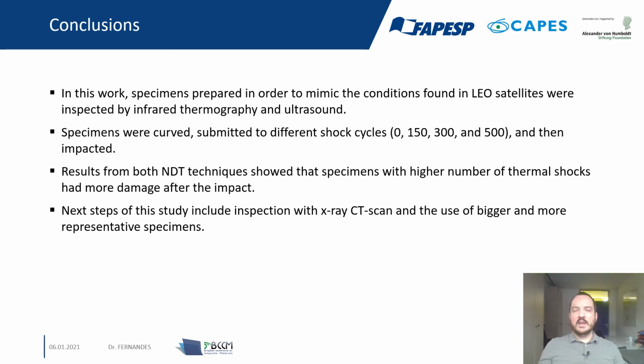In conclusion, in this work, specimens prepared to mimic conditions found in low Earth orbit satellites were inspected by infrared thermography and ultrasound. Specimens were curved and submitted to thermal shock cycles, and then they were inspected using infrared thermography and ultrasonic inspection. Results from both NDT techniques show that specimens with a higher number of thermal shock cycles had more damage after the impact. Future work of this study includes the use of other NDT techniques such as X-ray CT scan and eddy currents, and also to inspect bigger and more representative specimens.